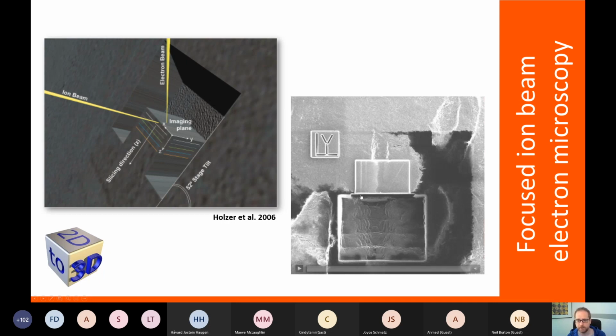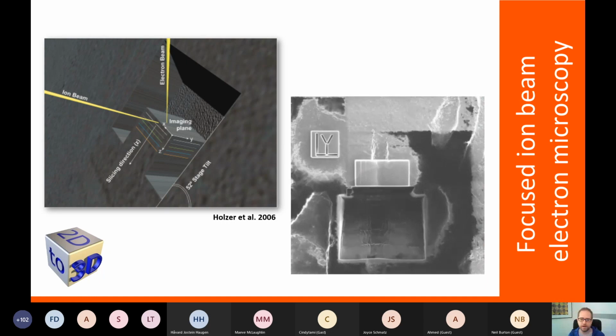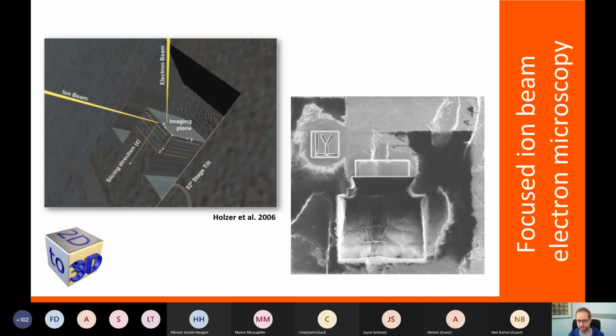This here is a platinum layer that was deposited onto the sample to protect the area of interest. This now probably also becomes much clearer why we need a gas injection system. We have to screen our sites of interest from the implantation of gallium or the general abrasion of the gallium ion beam by depositing a layer on top of it, which then keeps that area that we want to image undisturbed. And then we have this little fiducial marker here, for example, that allows us to correct for image shifts and keep the beam quite steady. So now if we play this video, you see how we have a sequential cutting throughout the material, and then the electron beam is imaging each of these slices.